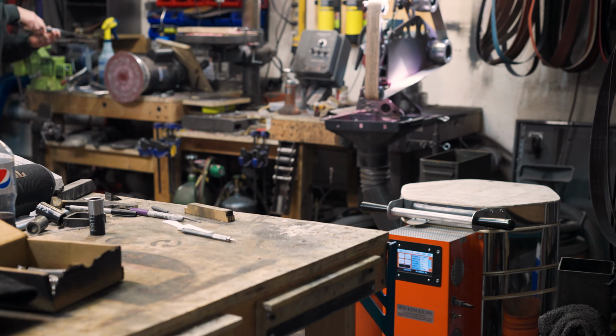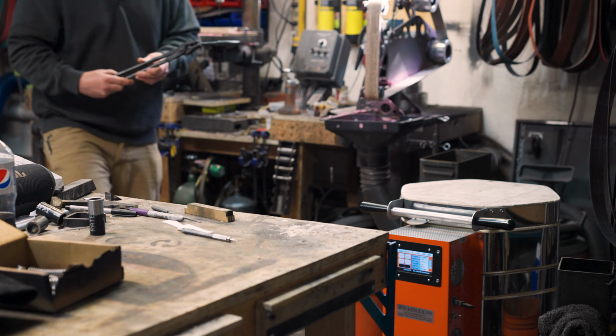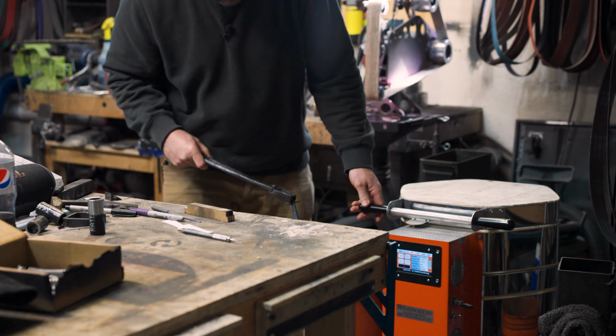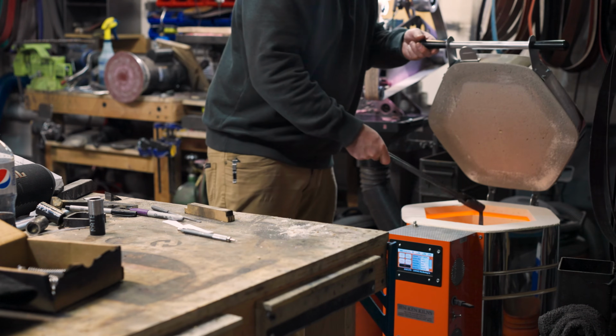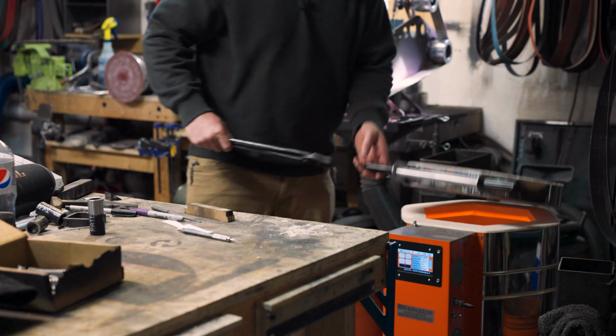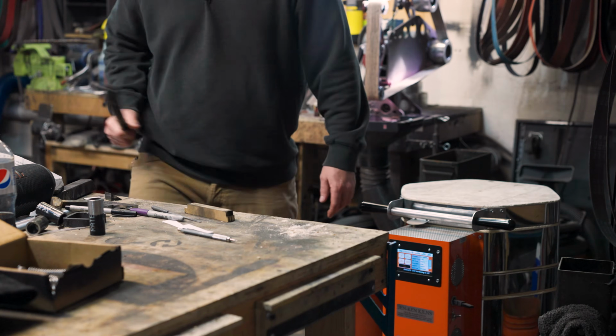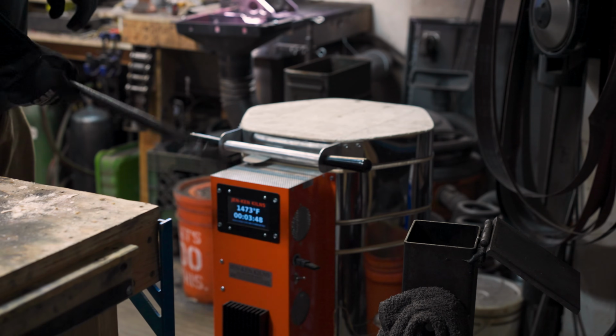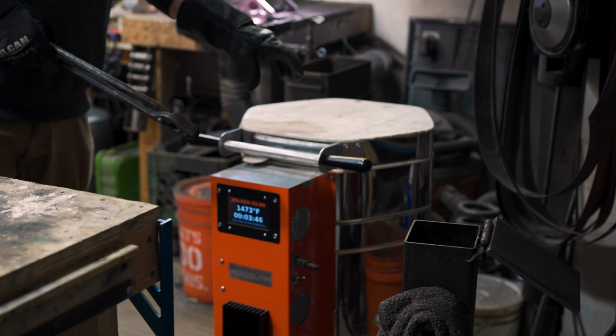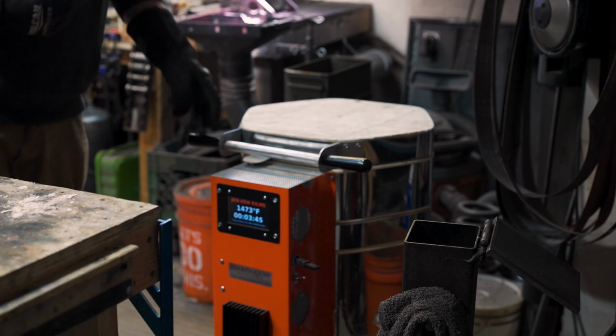Okay, I just checked this and we're actually all ready to black. So I'm going to throw it back in the kiln and get this thing up to heat and soaking. So we've had about a 12-minute soak, and I'm just going to go ahead and quench this right now.